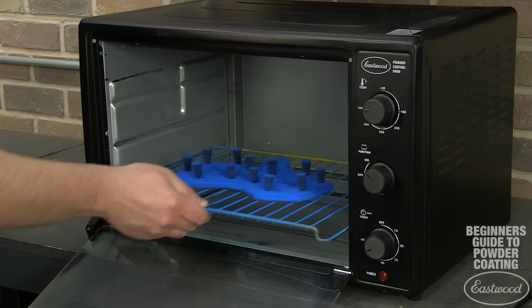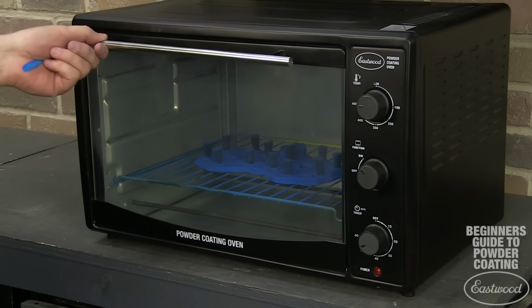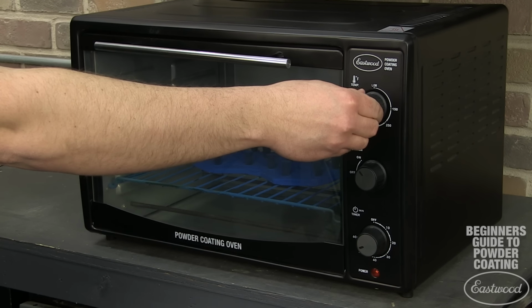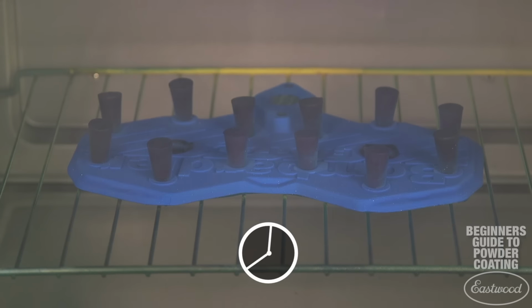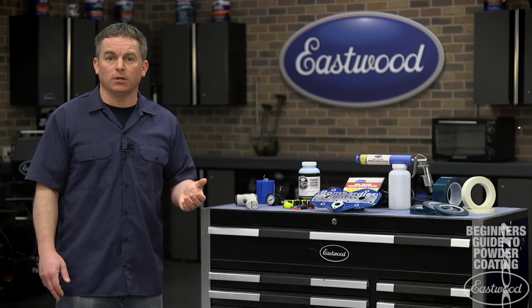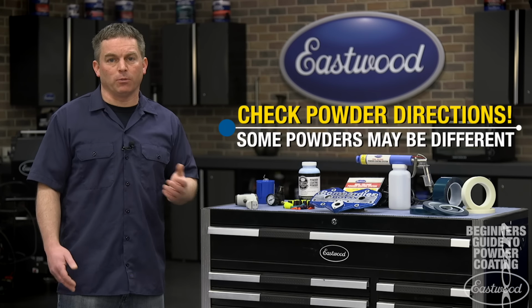Once the powder is applied, place the part in the oven to cure. We suggest curing the powder at 400 degrees Fahrenheit. Once the powder flows out and appears to be smooth, continue to cure for an additional 20 minutes. Remember, always check the instructions for the powder you're using for proper curing temperature and time.